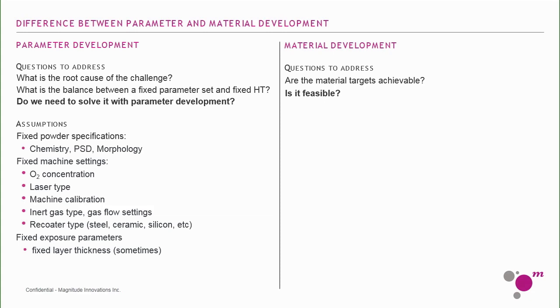And to some extent, we also leave the layer thickness constant, because just as a general thing, when you increase the layer thickness, your parameter windows actually narrow. And so if you're building something in a 30 micron process and then you go to a 90 micron process, well, you're going to have a lot harder of a time finding the parameter window that will actually be good for your application and actually across all the other applications that you'll develop.